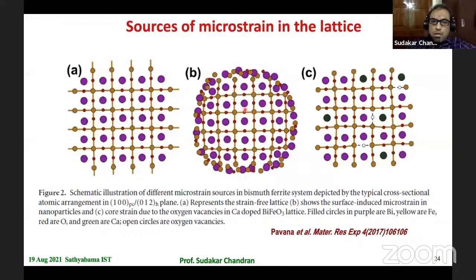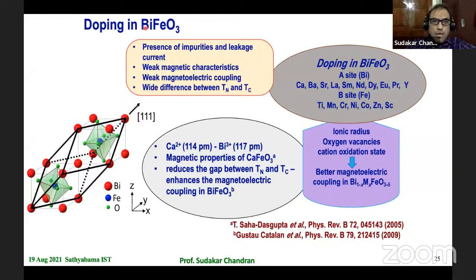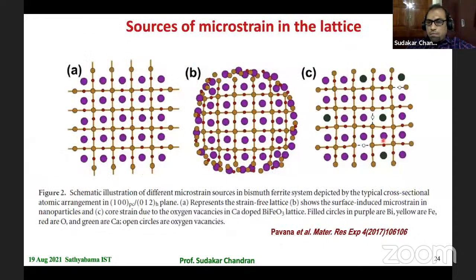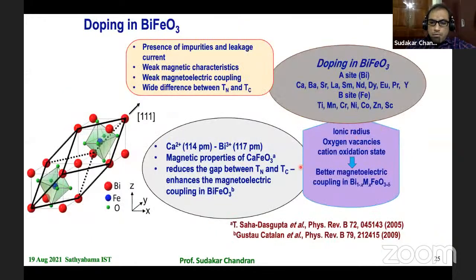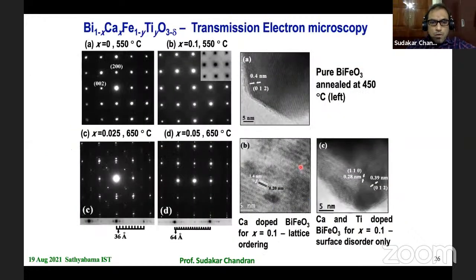The local strain can also be introduced into the lattice by introducing aliovalent cations, like instead of bismuth, you substitute some other similar ionic size cation, but with a lower oxidation state, which would introduce oxygen vacancies. So for example, here the oxygen vacancies are introduced because of the substitution of a different atom than the bismuth, as shown by the colors. So we did this calcium doped BiFeO3, and then of course calcium doping itself introduces a lot of complex changes in the structure, and it's also temperature dependent, the temperature of the annealing.